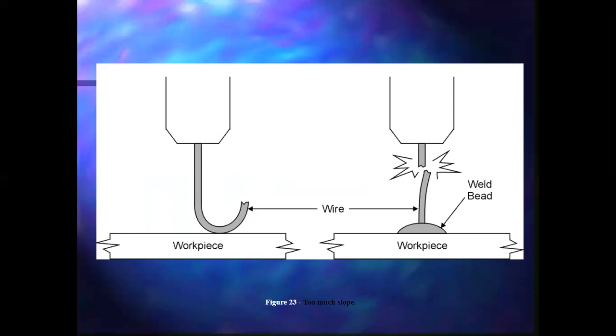So what can happen is you have too much slope in the workpiece here, and slope is referring to voltage and wire. In some cases, we can turn that wire feed speed up too much, and instead of having enough power to burn this off, the wire smashes off the workpiece, and it's called stubbing. It basically just bounces, bounces, bounces. Sounds terrible. It feels terrible on the gun. It looks terrible through a welding helmet. You've got chunks of wire breaking, spitting off everywhere. It's not creating that weld you want.